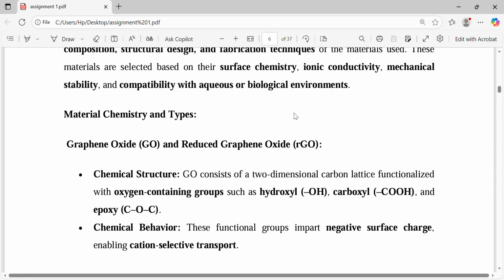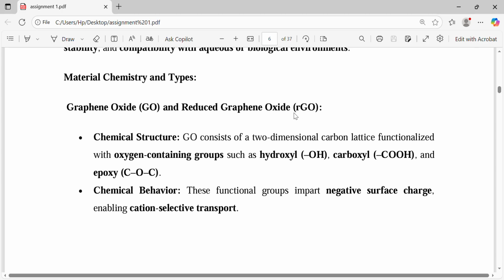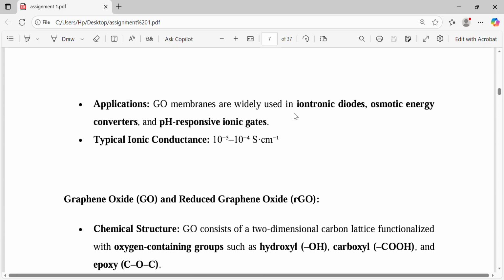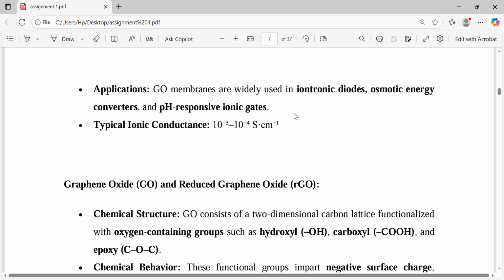Material chemistry and types. Graphene oxide and reduced graphene oxide. Chemical structure: GO consists of a two-dimensional carbon lattice functionalized with oxygen-containing groups such as hydroxyl, carboxyl, and epoxy. Chemical behavior: these functional groups impart negative surface charge, enabling cation selective transport. Application: GO membranes are widely used in ionic diodes, osmotic energy converters, and pH-responsive ionic gates. Typical ionic conductance 10 to the power minus 5 to 10 to the power minus 4 siemens per centimeter.